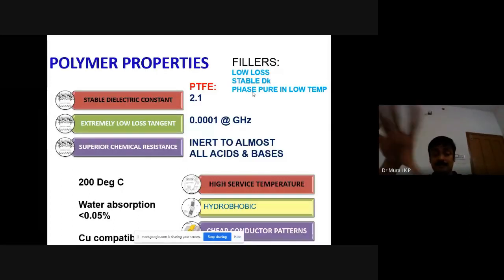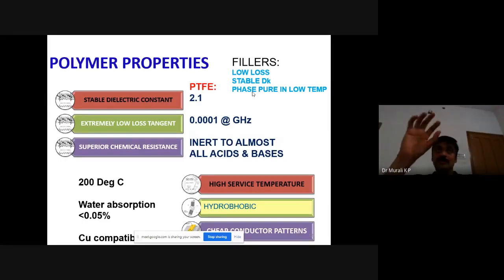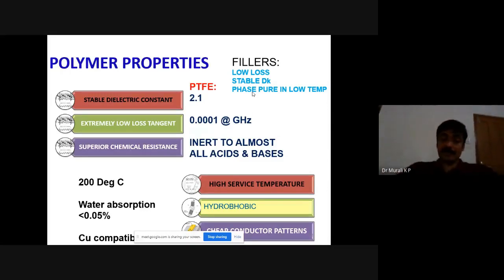And for fillers, we need ceramics having very low loss, or ultra high Q materials, with a stable dielectric constant and phase purity at low temperature. That is very important. Some ceramics will get the pure phase only at the sintering temperature, so it will be a bulk mass which cannot be used for this application. We should get the phase purity in the powder form in order to use it as a filler for substrate fabrication.